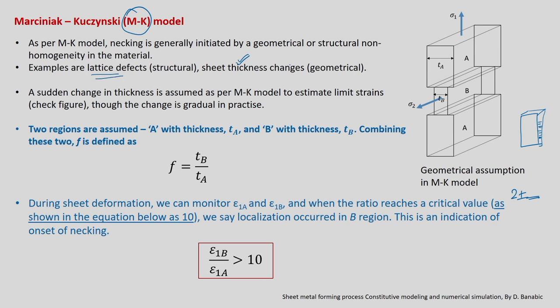As per this particular theory, we are going to assume a sudden change in thickness to estimate limit strains. This particular figure, we already introduced to you. However, we should know that such a sudden change is not actually true in practice. It's going to be a gradual change in practice. That's why I gave you different values here. So it's not going to be a sudden change, but this is the simplest choice we have.